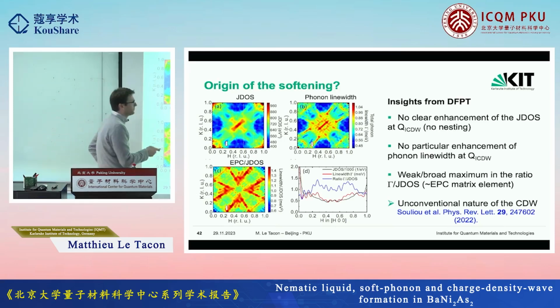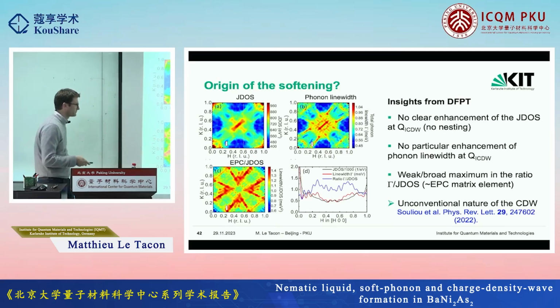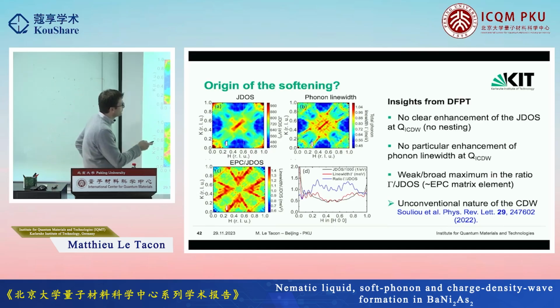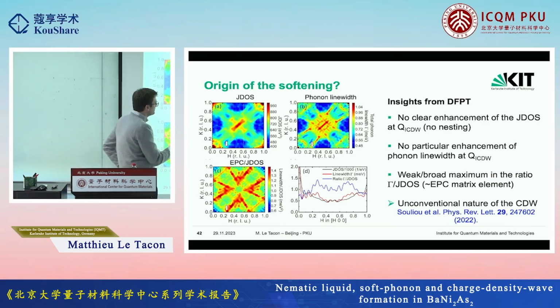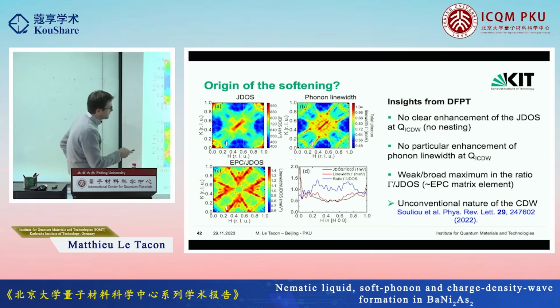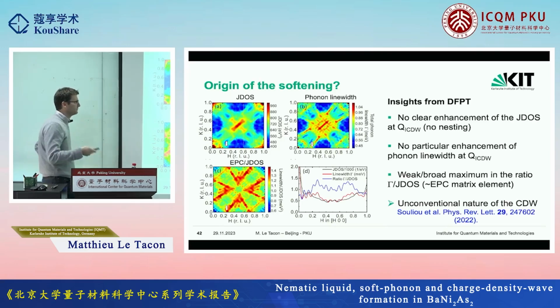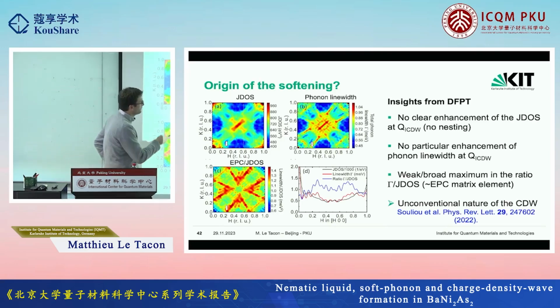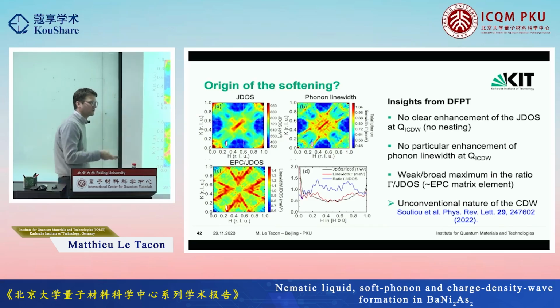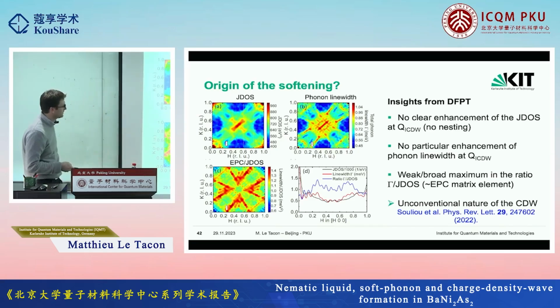You can calculate the phonon line width, which is a measure of the electron-phonon coupling, and this is actually the sum over all the line widths of all the phonons. So this is really the total electron-phonon coupling. And well, there is some kind of thing at that wave vector, but it's very shallow. I mean, that's basically the cut here. I wouldn't really call that a sharp maximum or a divergence or really strongly momentum-dependent feature. And actually, there are many more features at other Q which would deserve that better.